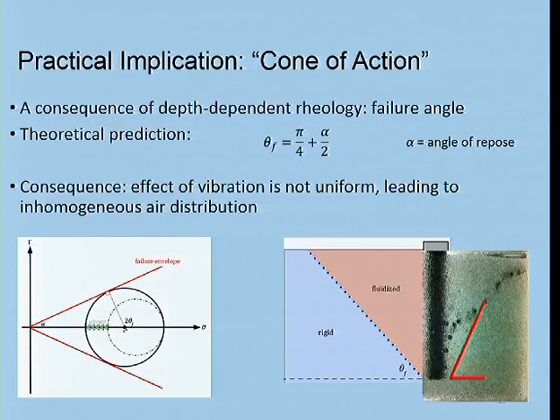One of the things we saw in our experiments is that this is an experiment that you see here where we have a surrogate fluid. It's a clear fluid that is a yield stress fluid with aggregate in it, clear glass beads. And these little black dots were originally lined up at the top of the sample. These are little steel balls. And they were stable when the sample was not being vibrated. When we vibrate this, that is, the vibration probe turns on, these balls start to sink and drift downward. And you can see that the ones closest to the vibration fell quite far. The ones far from the vibration did not drop at all. So there was this zone of influence where the balls drifted downward because the yield stress was defeated in this material and the gravitational pull could draw that ball to drop.